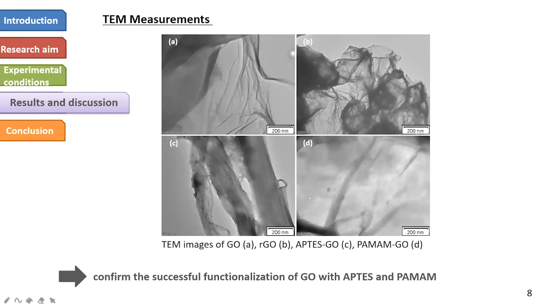Next slide. The TEM images reveal the characteristic morphology of the graphenes and confirm the successful functionalization of GO with APTES and PAMAM. Besides, it can be observed that in case of modified graphenes, especially the APTES GO, the thin film of the graphene is torn apart, forming threads. This means that we successfully stop the agglomeration of the particles. The PAMAM-GO seems to have some black spots on the surface that is attributed to the PAMAM molecules.